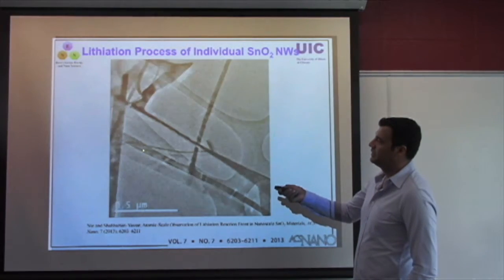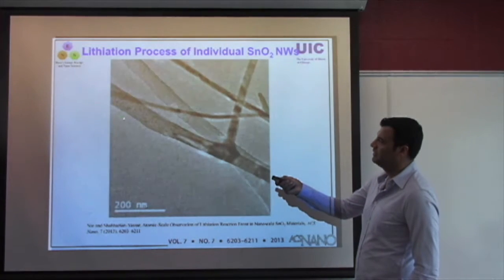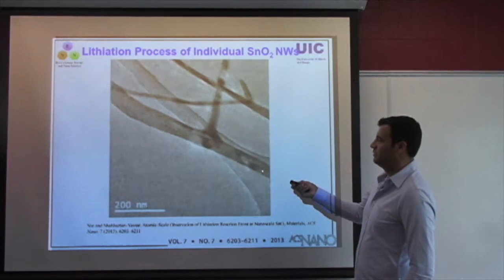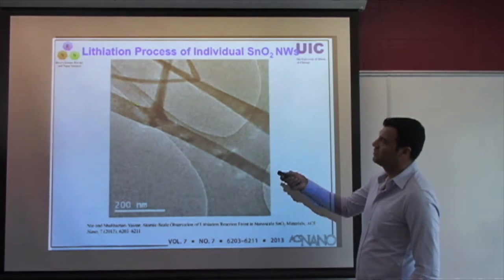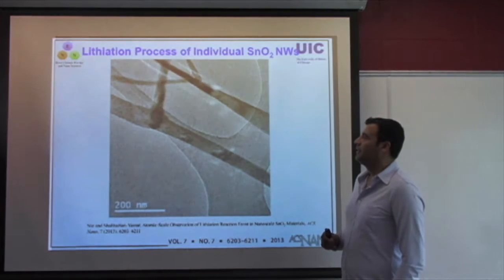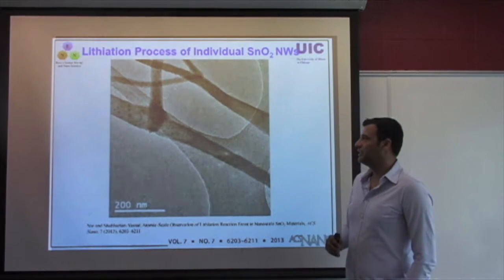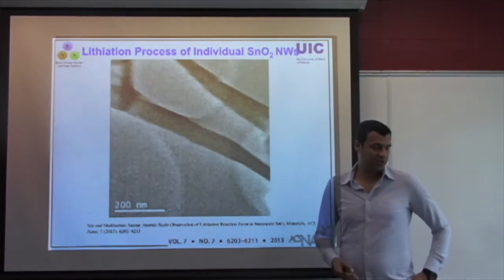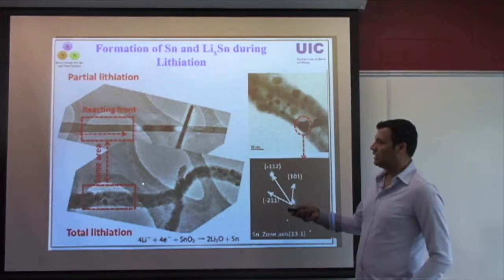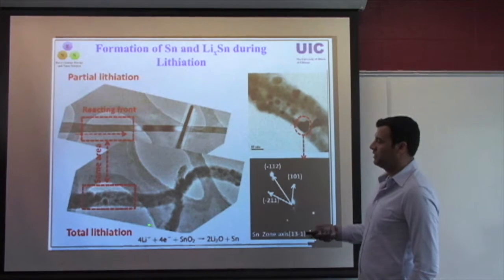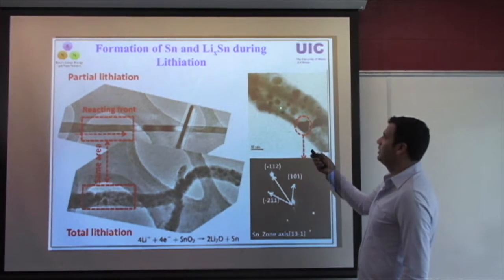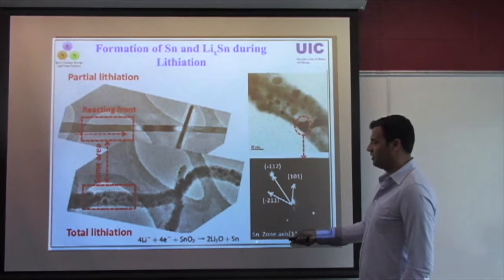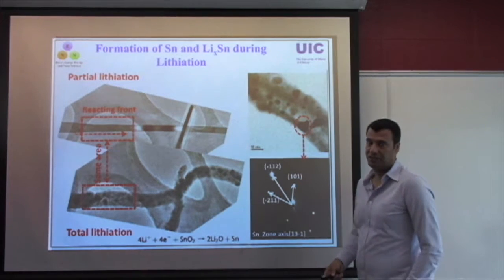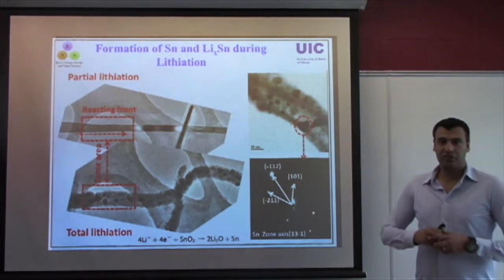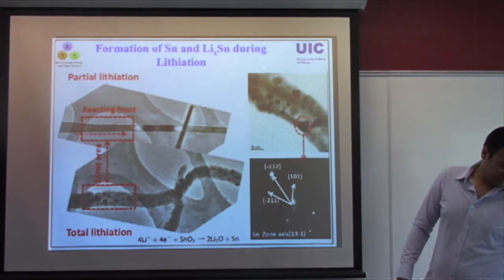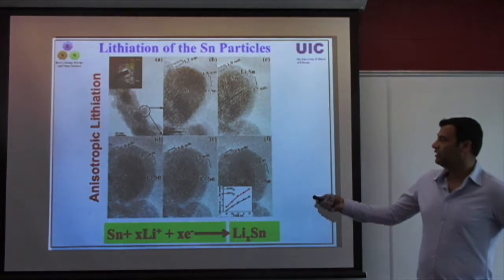What you observe here is some of these tin oxide samples that we lithiate, and we see the progress of lithium stripes in the sample, plus formation of some phases that are very interesting for us, because that indicates what stage of lithiation we are in. And if you look into what sort of structural change is involved with this, we see that most of this dark contrast particle is associated with the formation of tin, which indicates that we are in the conversion reaction stage. So we have a small amount of lithium intercalation, followed by this conversion reaction, and eventually the formation of alloys.